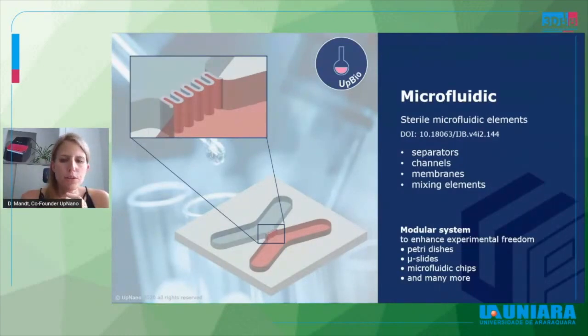When printing, you can then do separators, you can do some channel structures, or like in this case, the membranes. But you can also, of course, use some mixing elements. These structures can be defined individually. It's important just to make sure that at the end of the printing process, the remaining material can be removed again. So when printing circular structures from the top to the bottom of the whole chip, then the middle part is not developed, as you cannot develop the structure anymore. Therefore, you always have to make sure that you can apply a certain flow after the printing process to wash away the unpolymerized material.